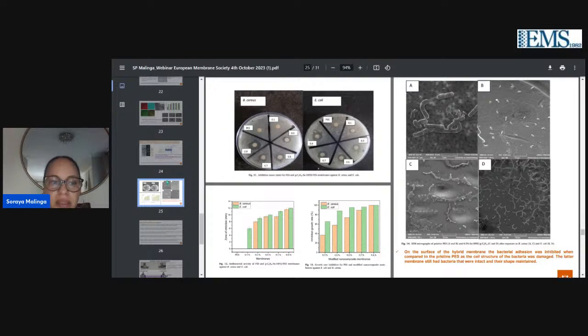result for the membranes. But with these membranes, I must say that we did have a reduction in flux. I'm still trying to figure out, but perhaps it is the shape of the particles, it might happen that there might be blockage of the pores, or yes, that needs further investigation. Because when we looked at the surface of our membranes on SEM, we could see that A and B, those are the unmodified. C and D, we can see that there's disruption of the actual bacteria, because you can see that the cell wall is disrupted, and there's no more bacteria that can be seen on the surface of the membrane.